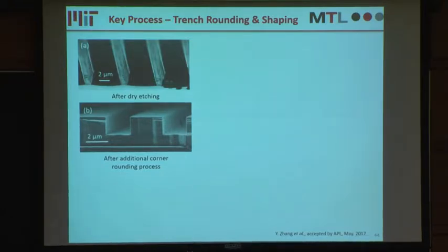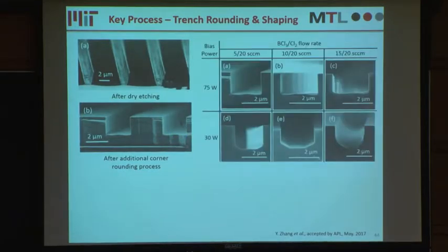So we developed a novel corner rounding process by utilizing TMAH and piranha clean. After this novel corner rounding process, we have a very smooth surface inside this trench, and all these corners have been rounded. We can further play with the dry etching conditions and combine these dry etching conditions with the corner rounding process.